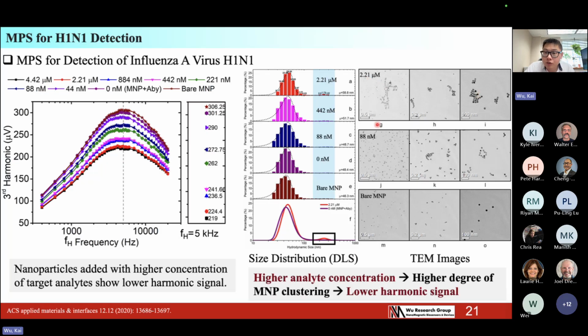With a lower concentration of the proteins, 88 nanomolar concentration of the proteins, the cluster is less severe from the TEM image. When there's no protein, the nanoparticles barely cluster in the TEM image, as you can see. So this further demonstrates that higher analyte concentration will increase the degree of the MNP clustering, which will lower the amplitude of the harmonics you can collect from the MPS device.